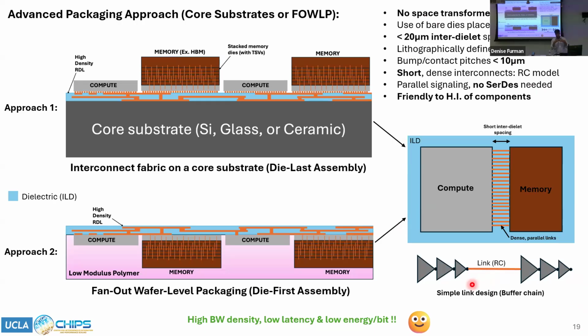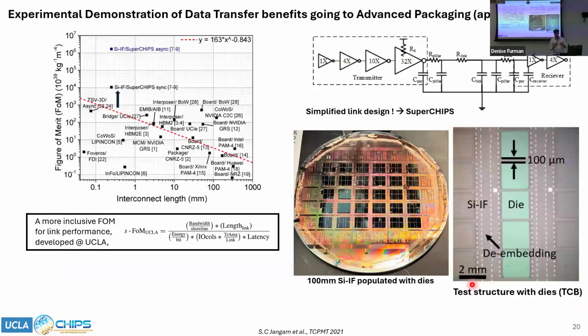So this kind of concept, it's not just a concept, it's something we have experimentally demonstrated, for example, at UCLA. So here you see, this is based on approach 1. This is actually a 100 millimeter silicon wafer, on top of which we did a dual damascene process and created two levels of metal wiring using back-end of line processing. And there are also copper bumps. There are 4 compute and 4 memory dies that are flip chip bonded on top of this interconnect fabric using copper-to-copper thermal compression bonding.